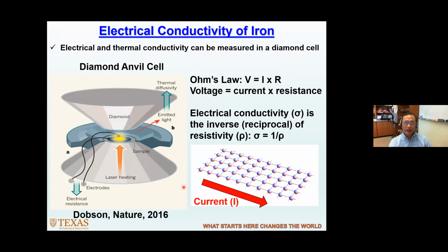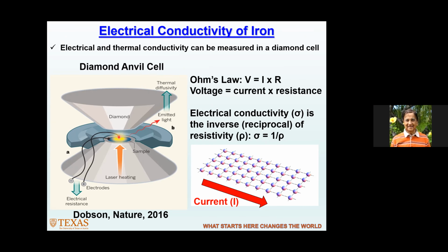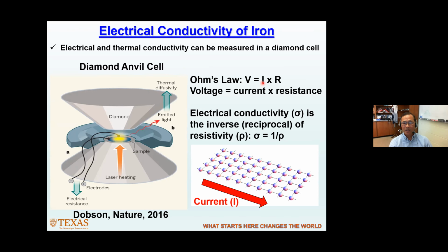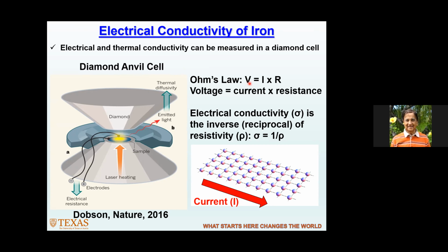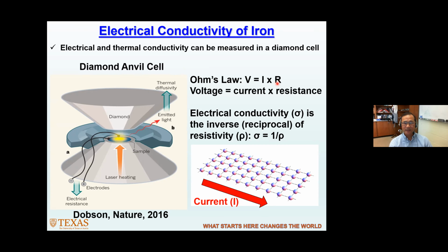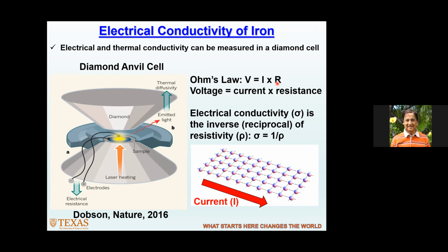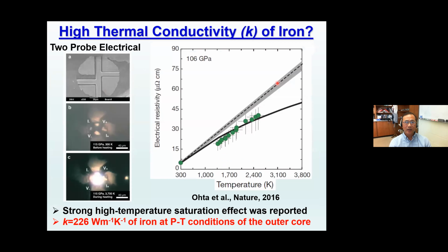All right, so the principle for the electrical conductivity measurement is very simple. Basically, you have a piece of say iron sample that you put into a diamond anvil cell, and you run current through the sample and determine the voltage change. From that, you can then determine the resistance of the sample. But in reality, the experiments are actually fairly tricky because of the sample shape and size, as well as the temperature gradient in the laser-heated diamond cell.